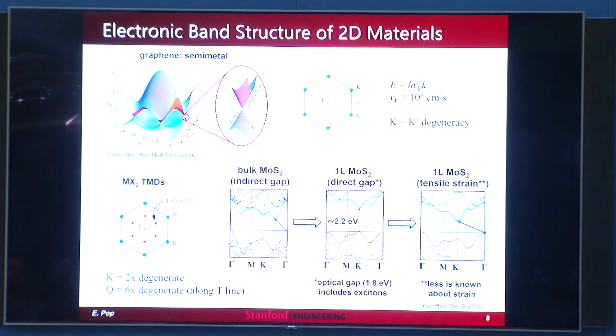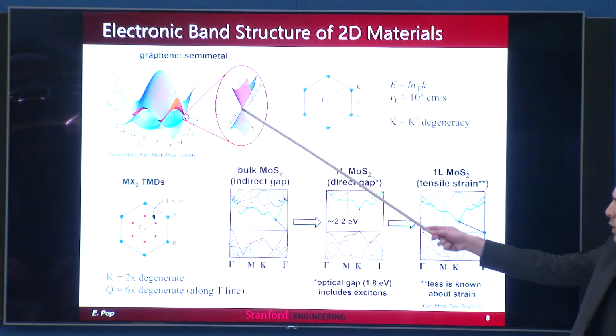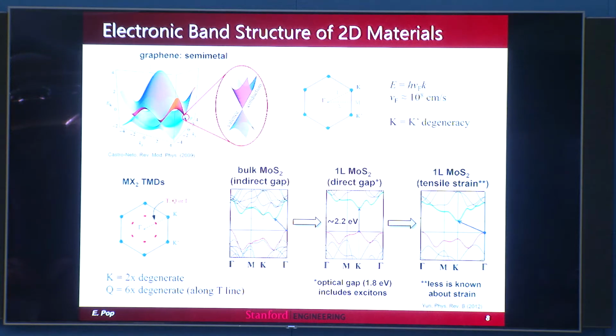I think it's nice to show the band structure and then the phonon dispersion of these materials. Graphene, of course, has this beautiful and very well-known sort of V-shaped band structure with very, very high Fermi velocity. This is 10 to the 8th centimeters per second, which is really fast. I mean, that's about a factor of 100 higher than saturation velocity in a lot of materials. But of course, there's no band gap, as you see over there, so that's a bit of a problem.